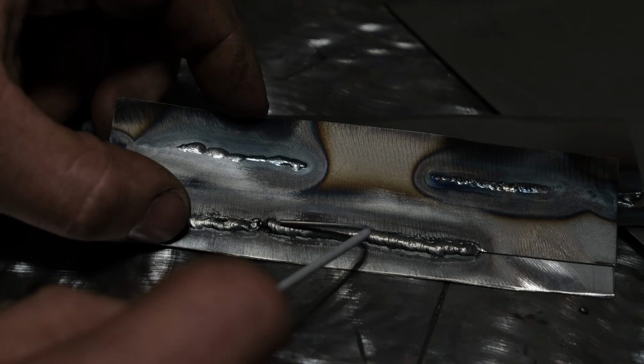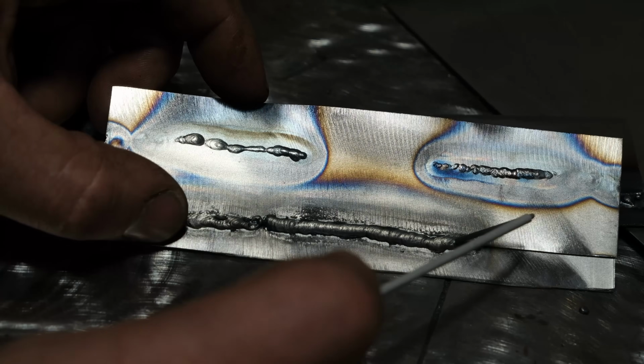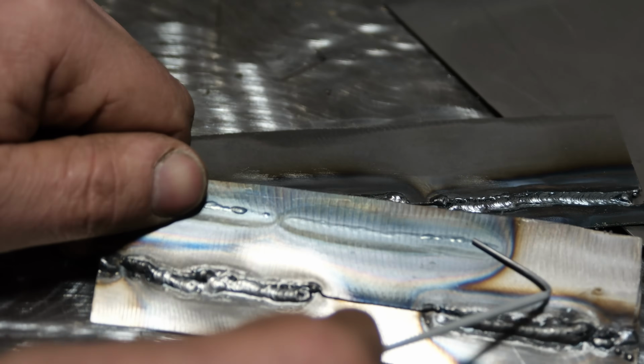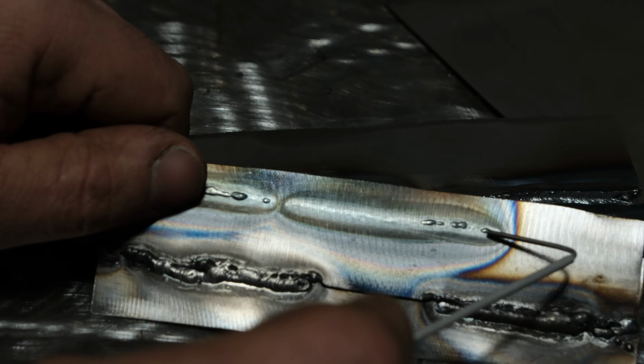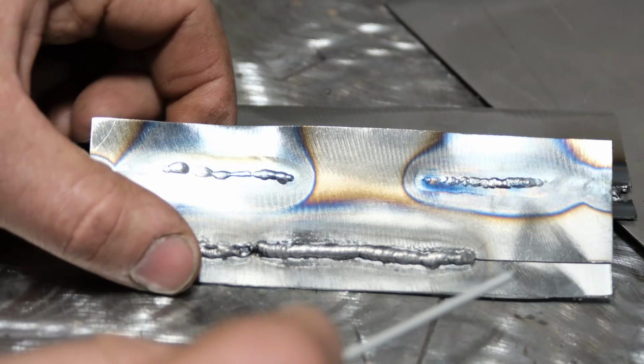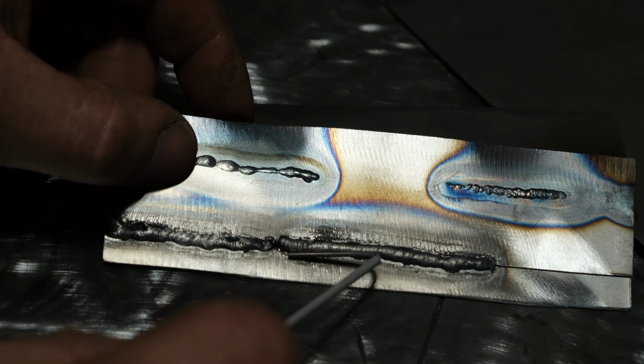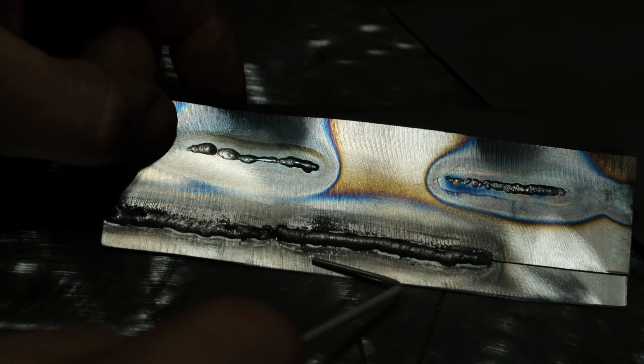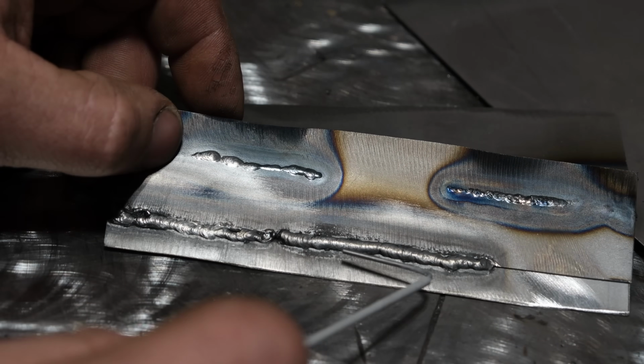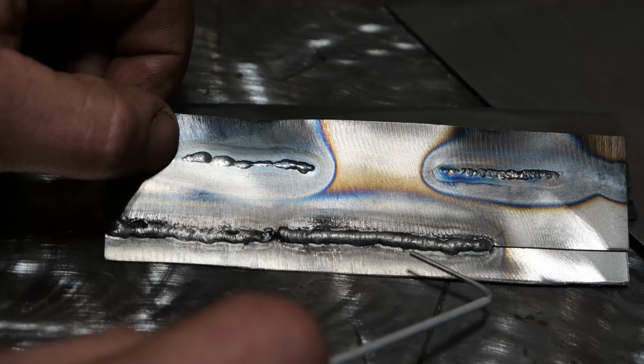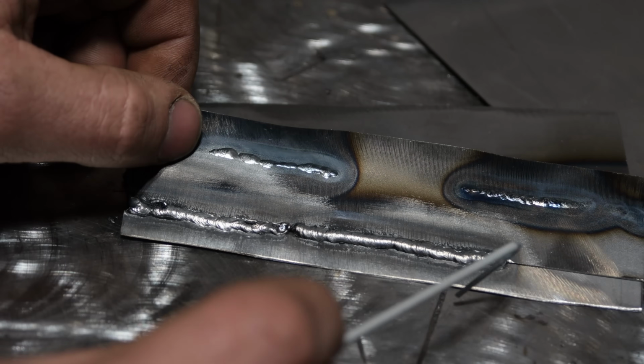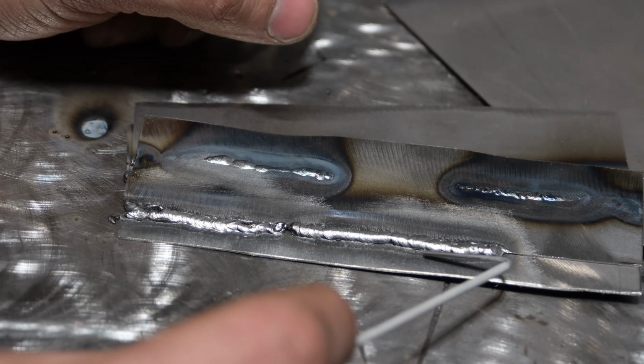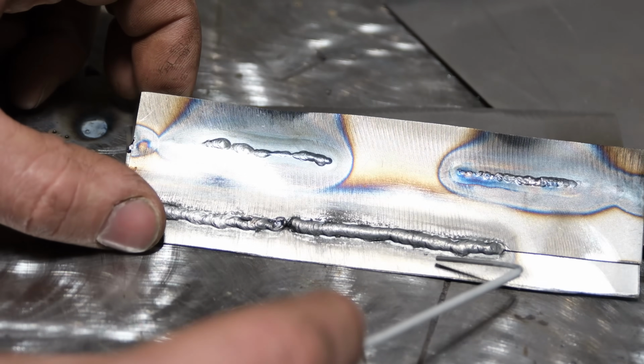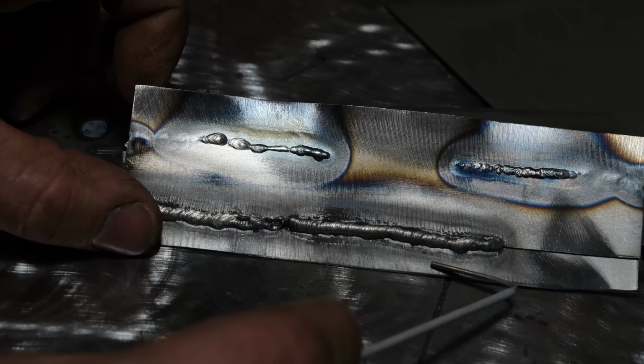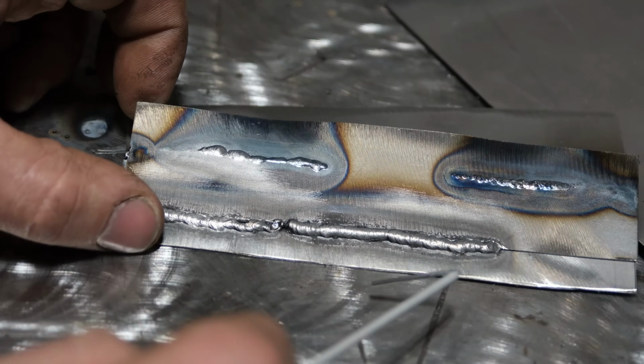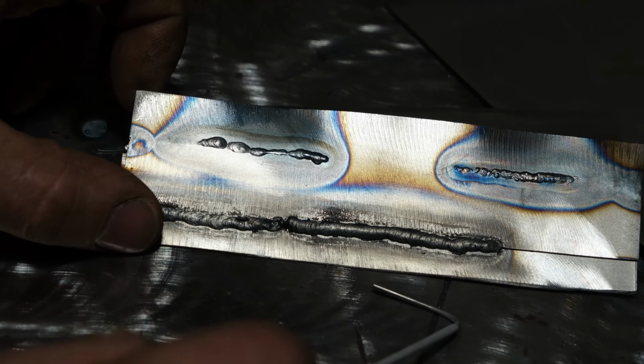But the overall appearance of this, yeah, it looks like a cold bead of caulk, but it did penetrate a little bit on the back side. I mean, there's a crease there and a couple of melt-through points. So this, I would say, is easy enough to do if you have a machine that can go down to 25 to 30 amps, and you run this DC electrode negative and use 6013. I did not try electrode negative 6011. It likely would work with these little rods. It's worth trying, but the success here is probably the most doable out of all of them.